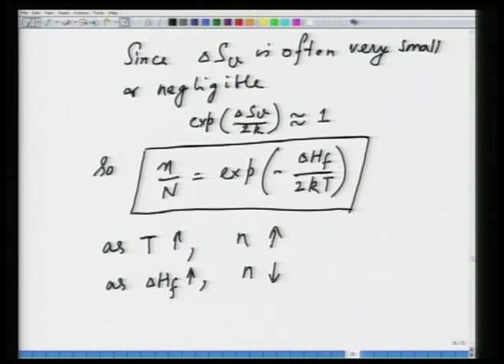Similarly, delta H f is enthalpy of defect formation, which you can guess represents the ease of defect formation. So, of course, materials with higher bond energy are going to find it much more difficult to form defects, and similarly materials with higher melting points will have, at one temperature, lower defect concentration as compared to those with lower melting points, because melting points are related to bond energies.